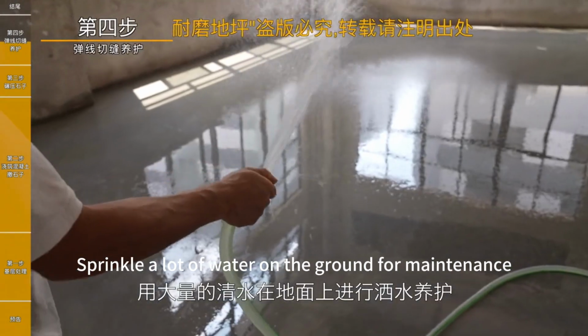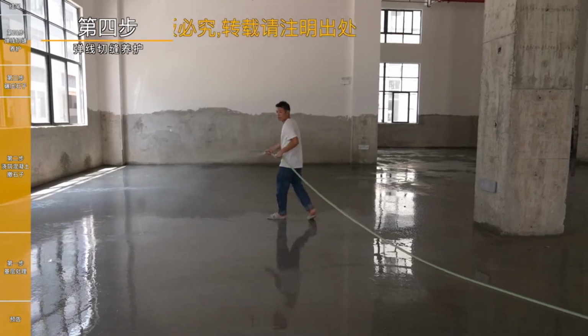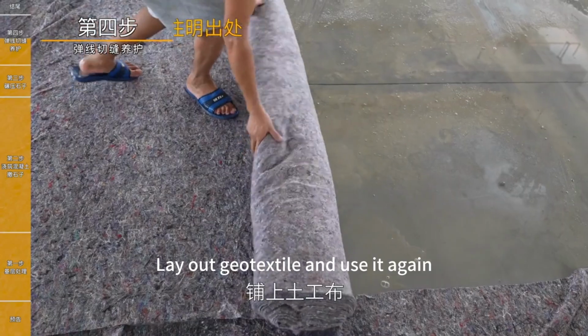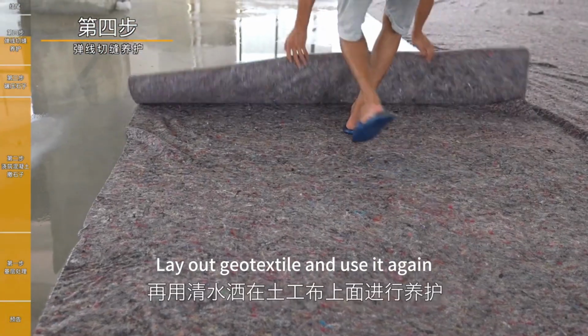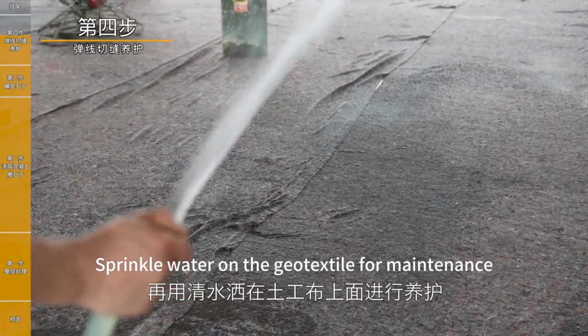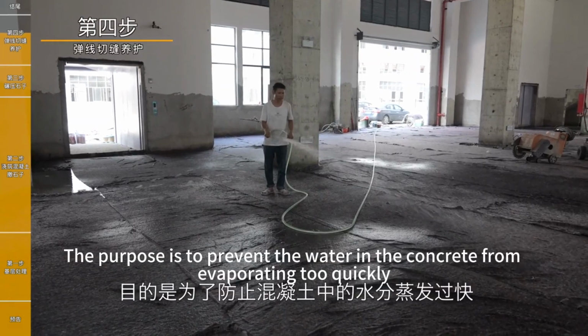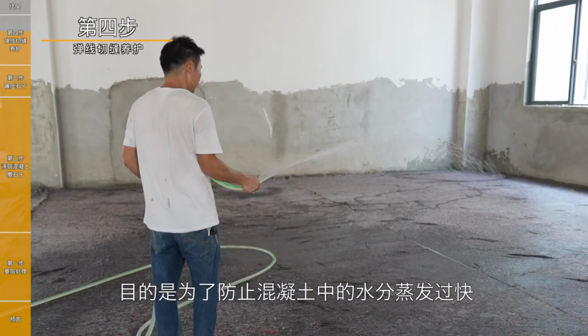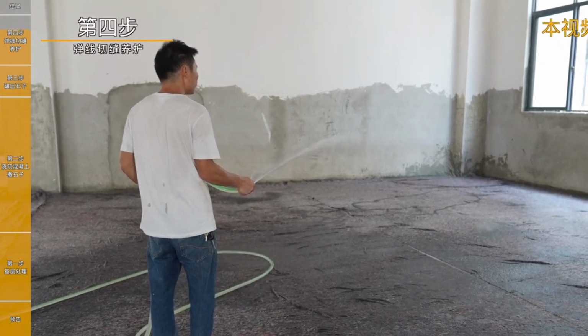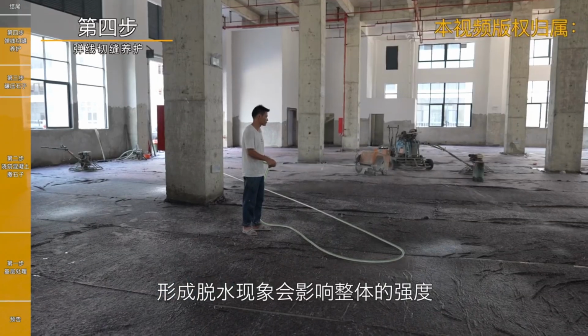Sprinkle a lot of water on the ground for maintenance. Lay out geotextile and sprinkle water on the geotextile again for maintenance. The purpose is to prevent the water in the concrete from evaporating too quickly. Dehydration will affect the overall strength and produce turtle cracks.